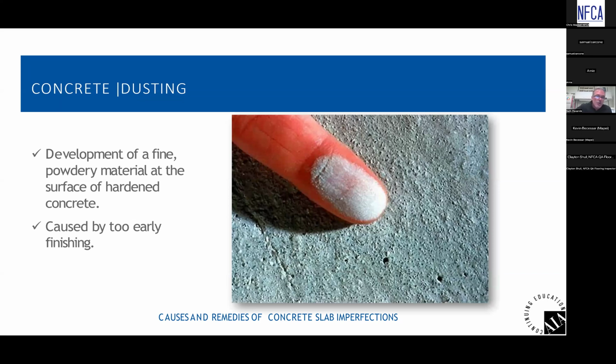Dusting is another situation, caused by finishing the concrete too early. And this goes back to the air bubble issue. If we get on concrete too early with a steel trowel, we can blister it. But if we also get on it too early and work the surface, we can bring too much concrete mixed water to the surface, and we basically overwater the surface of the concrete. So if you have concrete that's cured and it's dusting, you rub your finger on it and you've got dust on it, it's very common that it's a result of troweling the concrete too early.